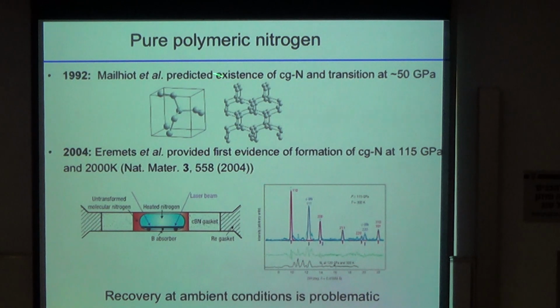So this single bonded form of nitrogen was predicted theoretically by 1992. It's called cubic gauche structure, and it was predicted to be stable at 50 GPa. Experimentally tried many times, but in 2004, Eremets and others synthesized this at 115 GPa and 2000 Kelvin. But what is important is that the single bonded form of nitrogen wasn't stabilized at ambient conditions. Once the pressure was dropped, this cubic gauche nitrogen decomposes into N2 molecules.